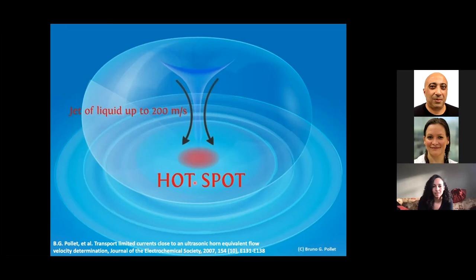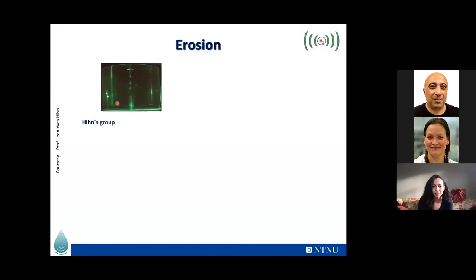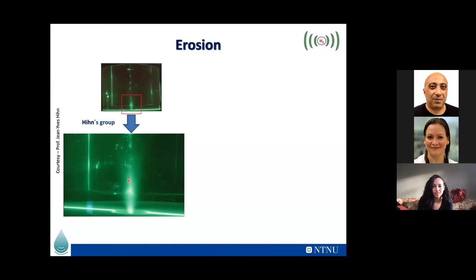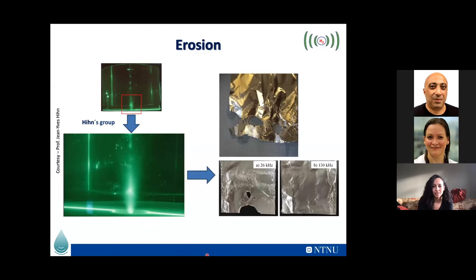All right, so erosion is very simple. This is your transducer sonicating at 20 kilohertz. This is a PIV imaging here, and you can see this intense area around the transducer. If you leave, let's say, aluminum kitchen foil for a few seconds, you will see pinholes and, in fact, quite a lot of damage around your aluminum foil. This is how intense ultrasound is.